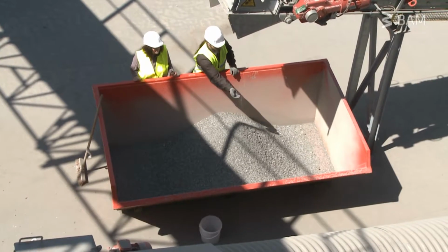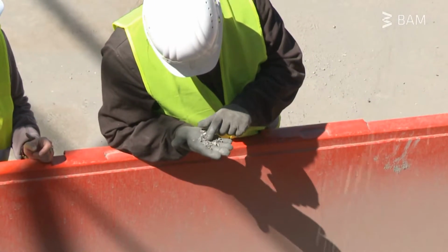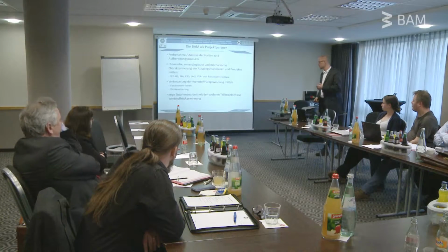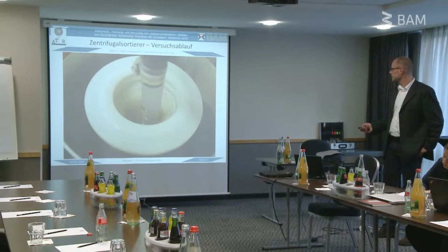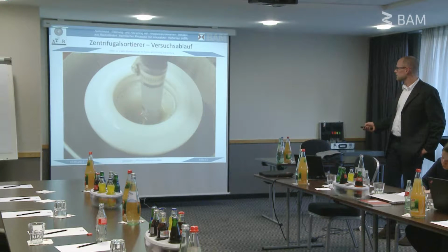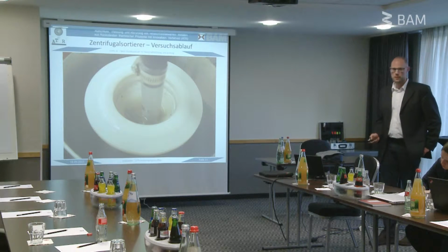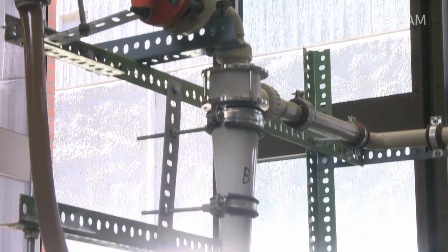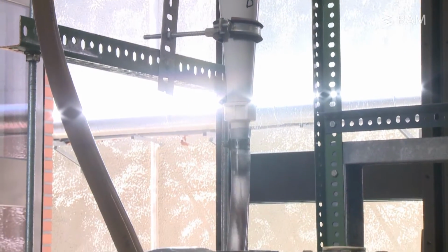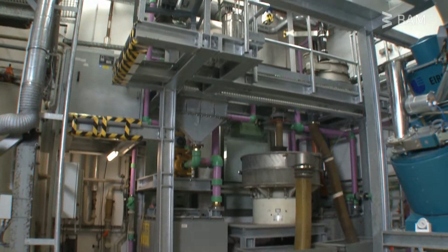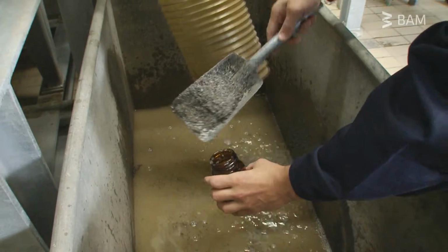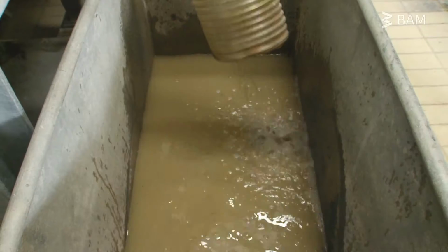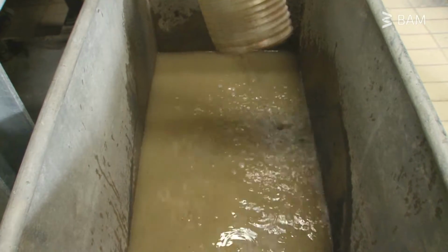In the framework of a joint project, the treatment of the fraction below 2 millimeters was investigated. Scientists of BAM experiment with different methods to refine this portion of bottom ash in order to generate ecologically harmless and marketable secondary raw materials. Therefore, treatment devices such as centrifugal classifier, hydrocyclones, or a jig in technical scale are tested. The procedures may be optimized to a high recovery rate of valuable metals, as well as to improve the quality of the remaining mineral aggregates.